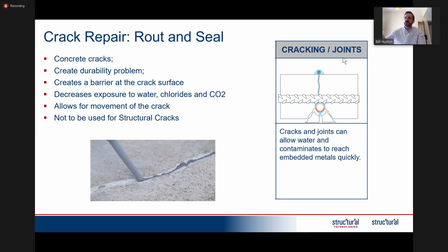One very simple way of repairing cracks is what we call rout and seal. This is where you simply rout out the crack and you seal it, and it basically provides a barrier that prevents water, chlorides, and carbon dioxide for carbonation from getting to the steel. Probably, it can't be used if you have a structural crack. If you have a structural crack, you need to do a proper structural repair. But a lot of these cracks are due to thermal expansion and contraction, so this allows that movement to be there.